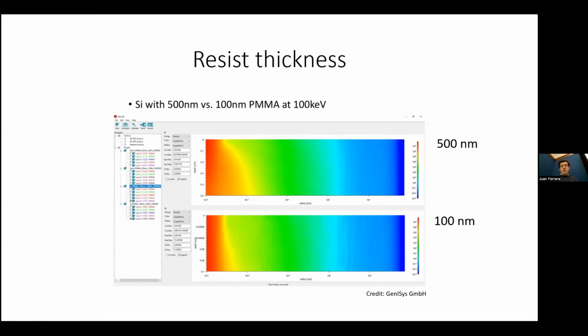Another interesting thing is that forward scattering increases with resist thickness. So if you're going to do a lift-off, like Mark will talk about later on, it's actually to your advantage to have a fairly large resist thickness, because you can see that as the beam forward scatters, you'll actually generate sort of an undercut pattern, which is something that you want for doing liftoff. It makes it a lot easier.